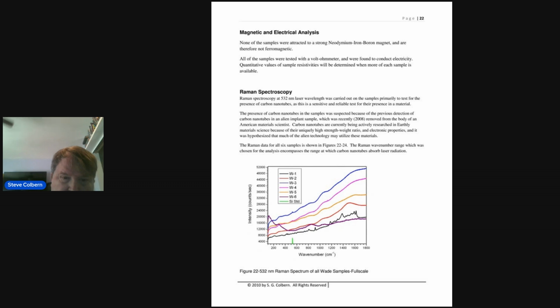And Raman spectroscopy, there were some intriguing indications there could be carbon nanotubes present, but I'd say overall it was somewhat inconclusive, except for sample W1. I thought at the time it had the most indications of having carbon nanotubes present. The one sample that I analyzed for Dr. Lear, and it came from patient 16 that had the pits in it I was talking about before, also had the highest concentration of carbon nanotubes that I'd seen in all these samples. There was no question that sample had carbon nanotubes. I didn't see any carbon nanotubes on the SEM shots because apparently the material was dispersed extremely well in the metal, and you couldn't see them. Probably they were present as individual tubes, but in any event,